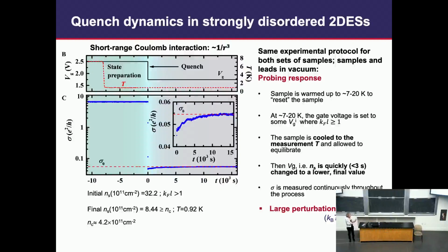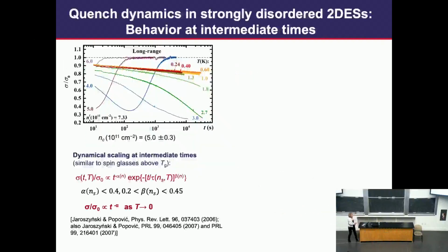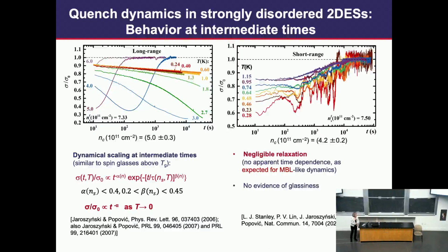So I want to compare the two cases. On the left side we have, again, the glassy case — the data are just taken at a different density, and this is what I told you before: the system goes away from equilibrium, back up. Then in the short-range case, this is what we get for basically the same density.